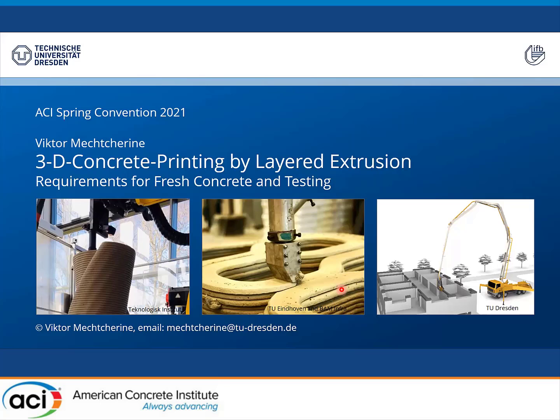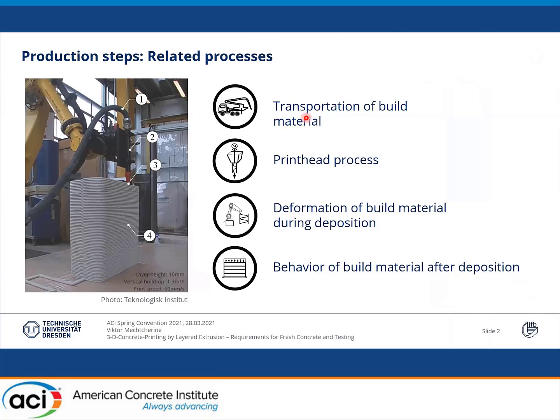While individual approaches within this group can differ considerably with respect to their material concepts and equipment, all of them rely on sound interaction between materials and machine along the processing chain. Generally speaking, the major processing steps are similar in all extrusion-based manufacturing approaches. They all include transportation of build materials to the printhead, the printhead process — meaning extrusion — then the deposition of build material accompanied by its deformation, and deposition of further layers accompanied by loading of each deposited layer by self-weight and process-induced forces, as well as related deformation of build material.